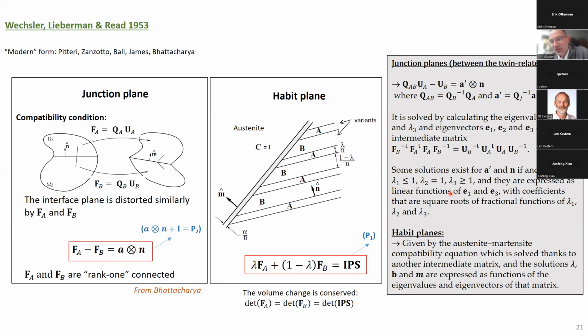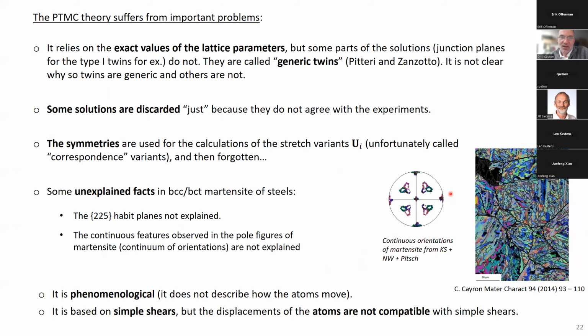But it is nice because there is nearly no input parameter here. But to me, and it's my personal opinion, I'm not so comfortable with it. Why? Because these two versions rely on the exact value of the lattice parameters, if the results rely on it. And once you do your calculation, you realize that some part of the solution, for example some junction planes for the type 1 twins, do not rely on the lattice parameters. So it means that you do a lot of calculation taking into account the lattice parameters very exactly, but at the end some solutions do not depend on their exact value.